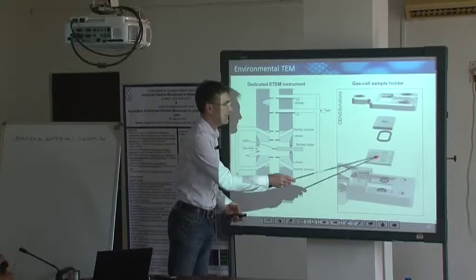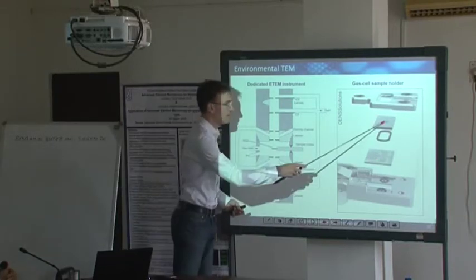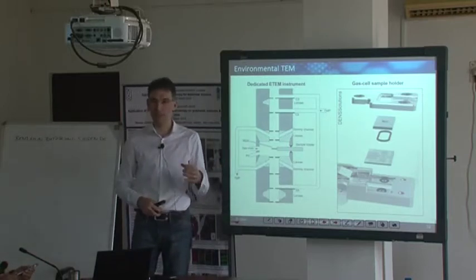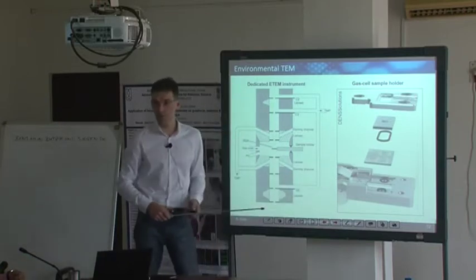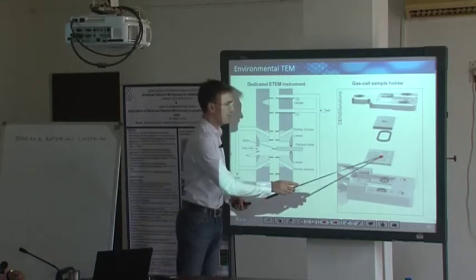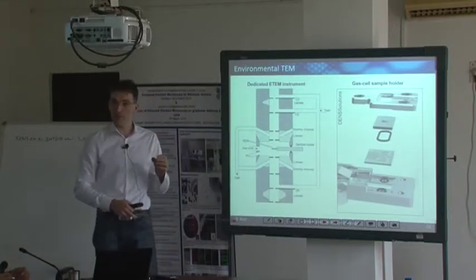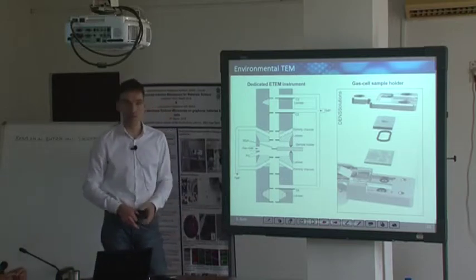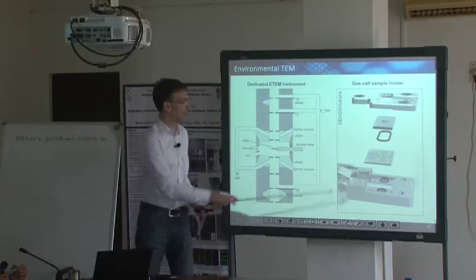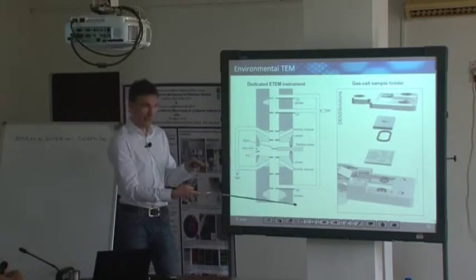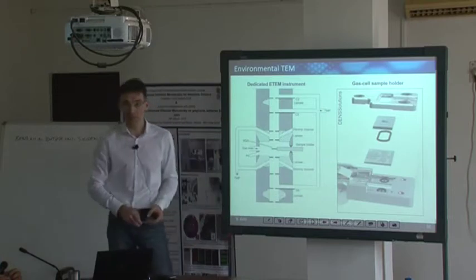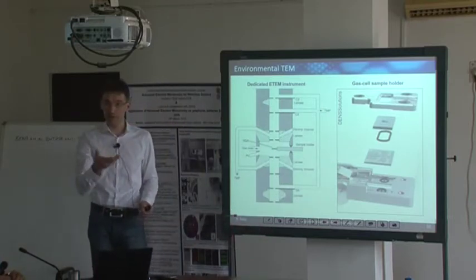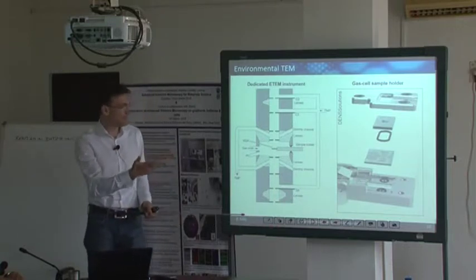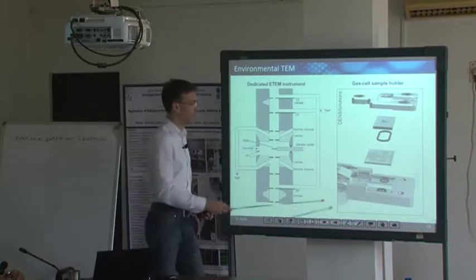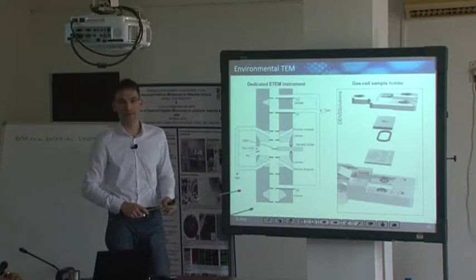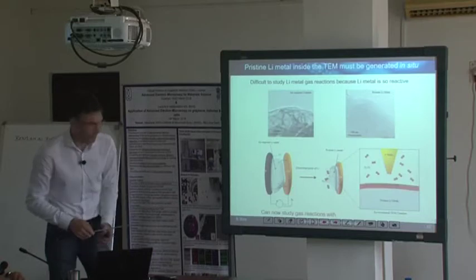This specific holder solution allows for both, and you have to imagine that those membranes are very small. So even at 2 bar pressure, which is a common range that you might achieve, the force on these very thin membranes is so low that they wouldn't fail. This is the reason why you can go to far higher pressures. And the thickness of your gas layer is commonly of the order of a few micrometers. So you have to penetrate with your electron beam through your confining membranes, through the gas environment, and finally through your sample. But nonetheless, at 200 or 300 kilo electron volts, you get quite decent atomic resolution data of that.